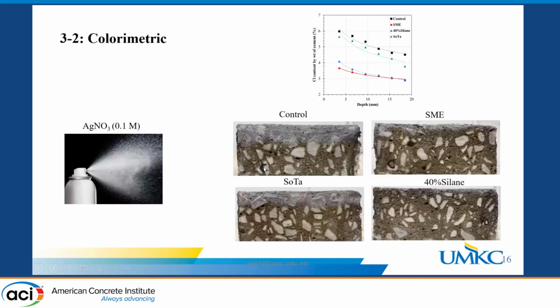So we characterized our specimens using the colorimetric method as well. We can see here, after cutting our concrete sample into two halves, we applied 0.1 molar silver nitrate. After a while, because the silver nitrate reacts with the chloride and forms silver chloride, which is white, we can see that in all of the control samples there is more chloride penetration, and the sodium tartrate treatment is a little bit less. However, we can see very little in the soy methyl ester and silane. This colorimetric data is very consistent with the chloride profiling.